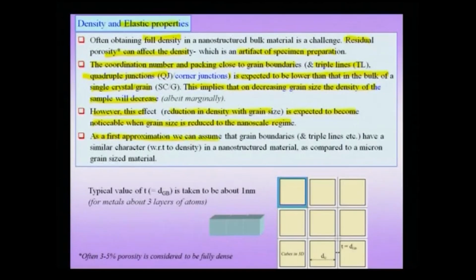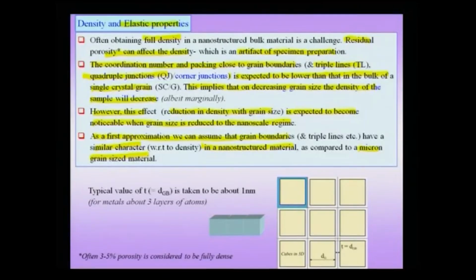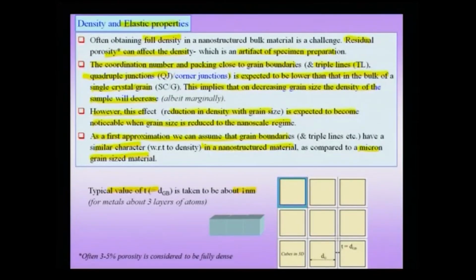Okay. As a first approximation, we shall assume that the grain boundaries have a similar character in nanostructured material. This is a very drastic assumption, but we will assume that even though we are going to nanostructured material, the overall crystal structure of the grain boundary, the grain boundary widths, etc., remain very comparable or very similar to that in a micron size material. This is a drastic assumption, but it will help us make a simplification in the calculation. Additionally, we will assume the value of the grain boundary thickness, which is a quantity based on a definition: the region close to a grain boundary where there is a disturbance of the atoms from the expected lattice position, I call it the grain boundary region. This is typically less than about 1 nanometer, but for simplicity here we will assume that it is about 1 nanometer, and in metals typically it has been found to be of the order of about 3 atomic layers.